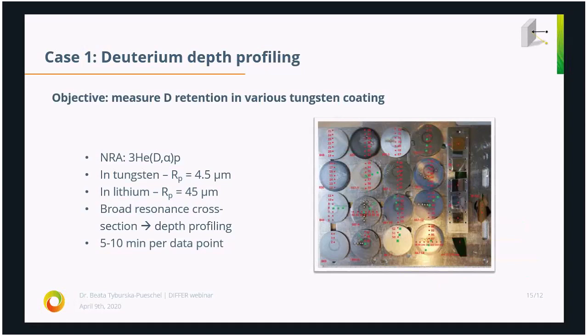Thanks to it being so fast, since I collect the data across the entire sample, I can say, for example, whether deuterium plasma exposure was uniform or not. Is there any flaking of the coating along the sample, etc. If this were a slower technique, I just wouldn't be able to collect all that data. And quite frankly, analyzing this data takes me longer than measuring it.